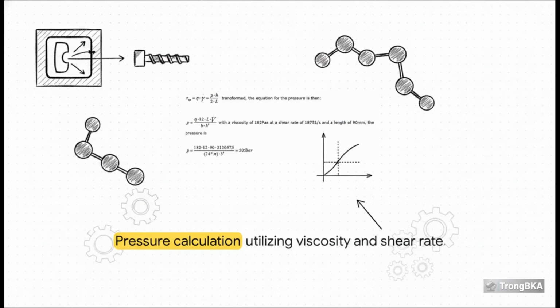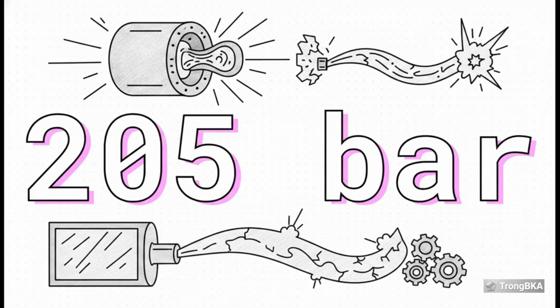Which brings us to the ultimate calculation: internal die pressure. Engineers take the complex geometry of the die, calculate the volumetric flow rate based on the pulling speed, and determine the exact shear rate. In our example here, at a shear rate of 1875 reciprocal seconds, the polymer has a known viscosity of 182 pascal seconds. We plug all of this into the pressure equation, and we get our final answer. And the result of that formula is a staggering 205 bar. Just to put that into perspective, that is over 2,900 pounds per square inch of pressure building up inside that tiny metal die. This highlights the extreme physical forces required to perfectly shape the plastic at the very end of the line, and exactly why the mechanical design of the tooling must be absolutely flawless to prevent a catastrophic blowout.